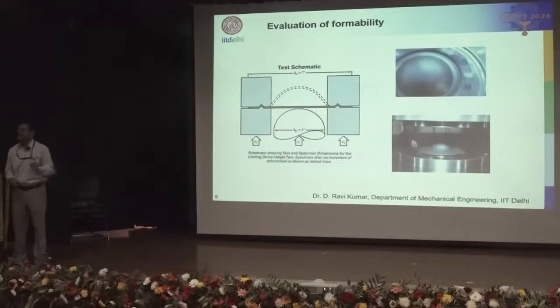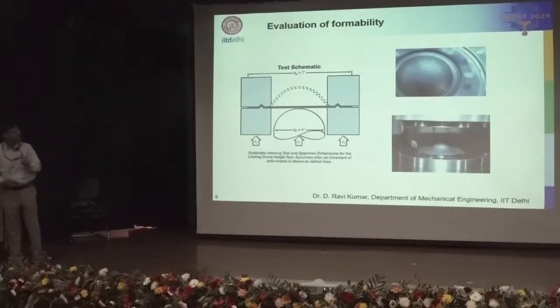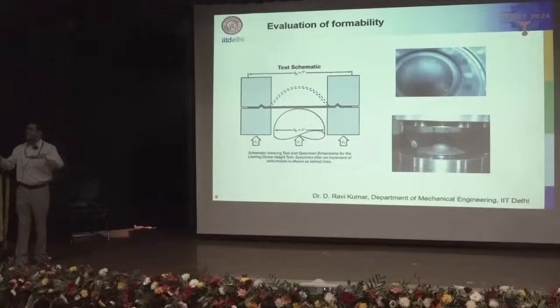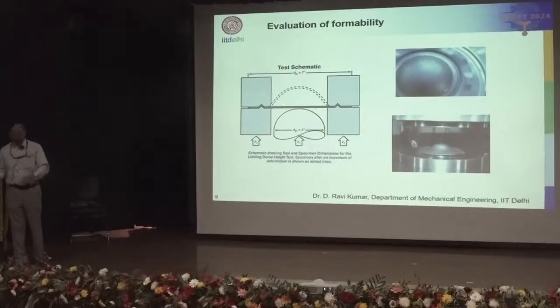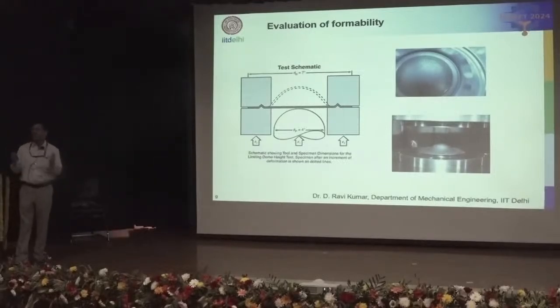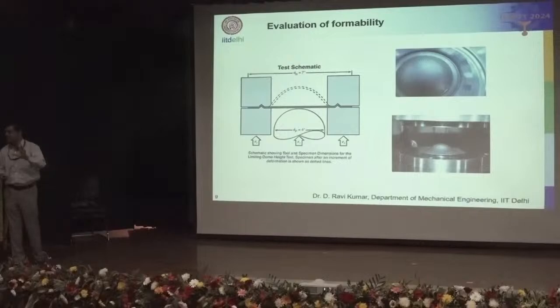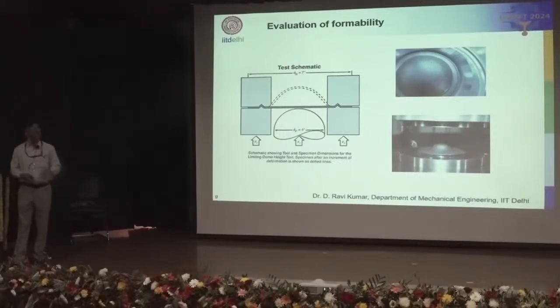So for example, a limiting dome height test is shown here. We use a hemispherical punch to deform a sheet until a visible necking or failure is observed. Here the edges of the sheets are completely clamped so that the material undergoes pure biaxial stretching. So it gives us a measure of stretchability. Similarly, if I want to determine drawability, we have another test called Swift flat bottom cup test, where we measure the limiting draw ratio, the maximum possible draw ratio which can be achieved without any failure. Similarly, there are many other tests, Erichsen cup test, Fukui conical cup test, and so on.